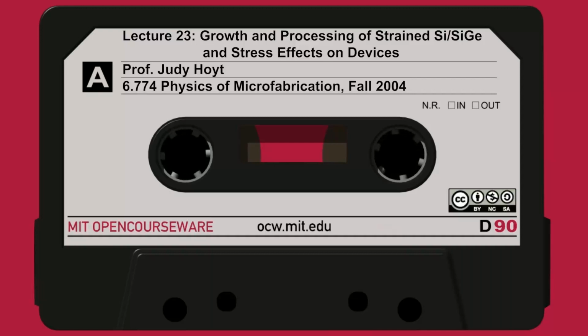Unless you go to very high germanium contents. There's some data here with a 40% substrate. So that means the strained silicon layer is very thin and it's strained to a 40% substrate. Here, for the mobility enhancement factor, there's not a full curve available. The highest field these people went to was about 0.6. But they did get pretty large enhancement factors. So it looks like if you're going to use biaxial tensile strain in the silicon, you need to go to very high levels of strain if you want this to work. So that's one big disadvantage for the P MOSFET in this technology.